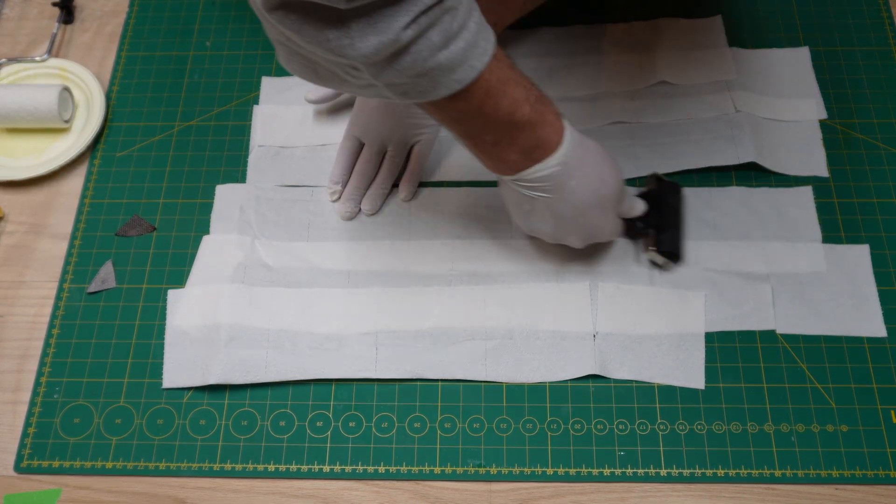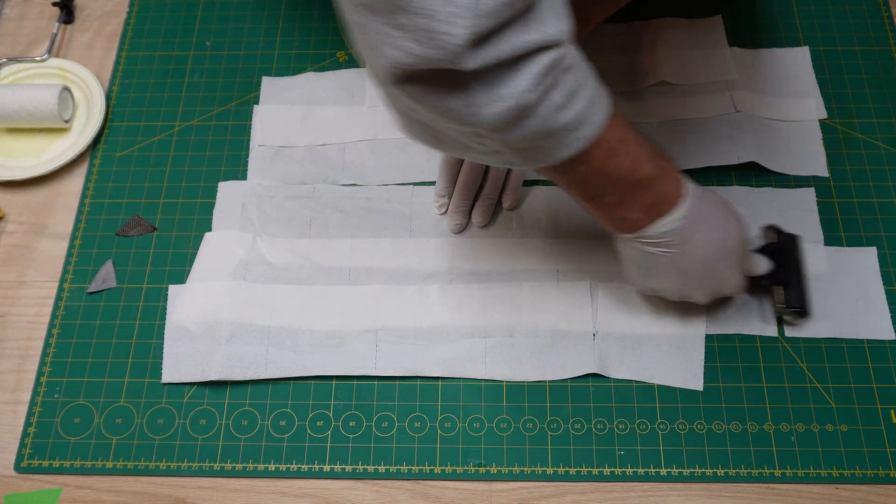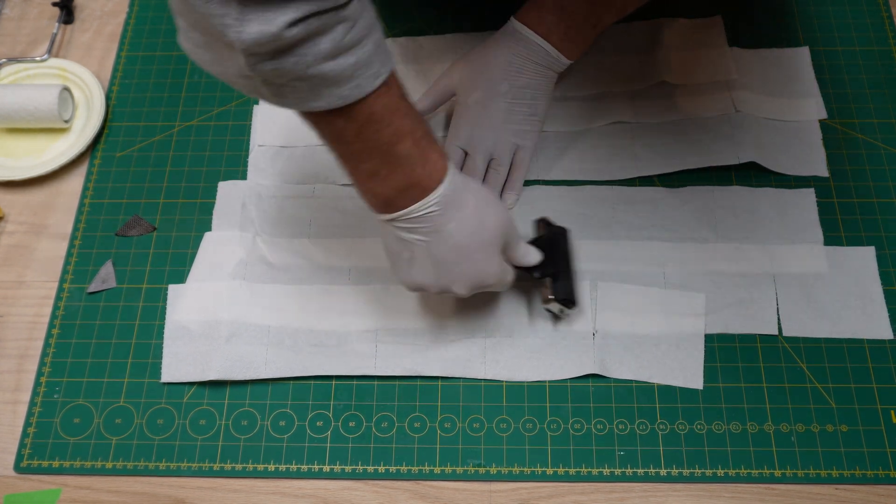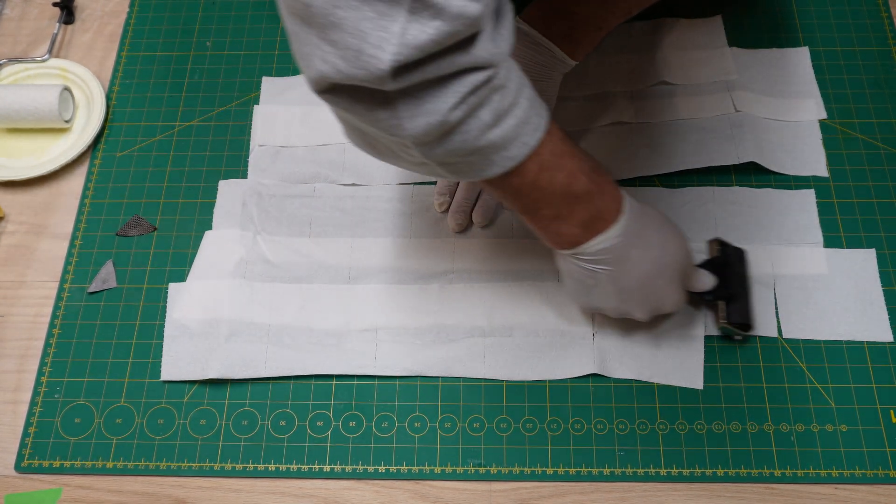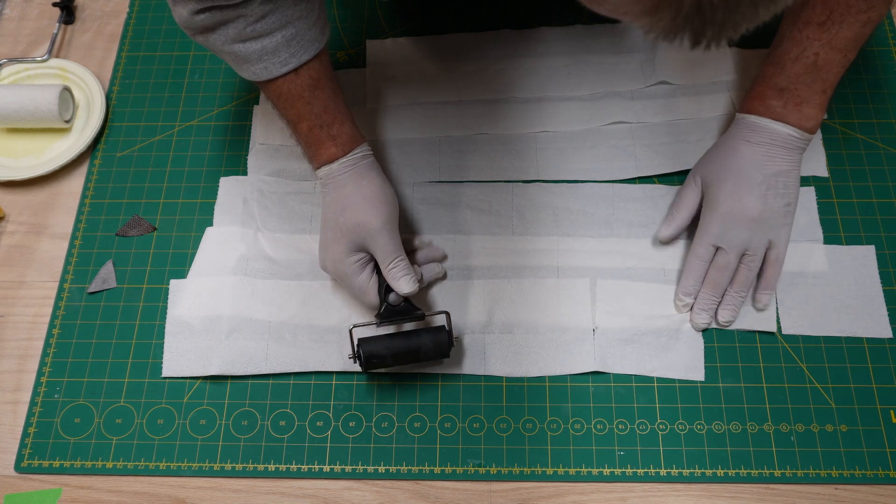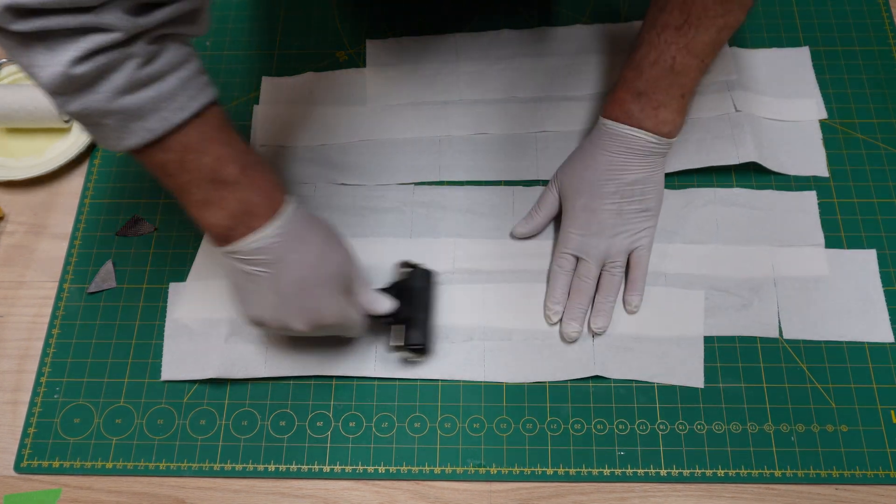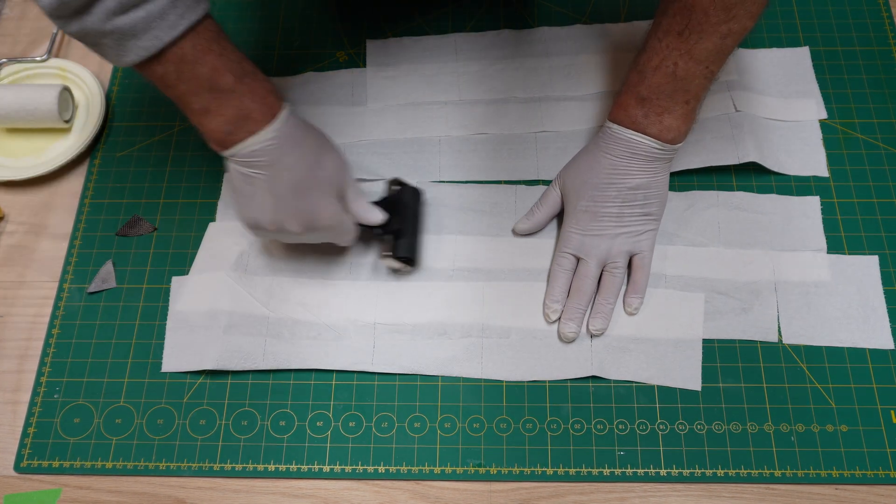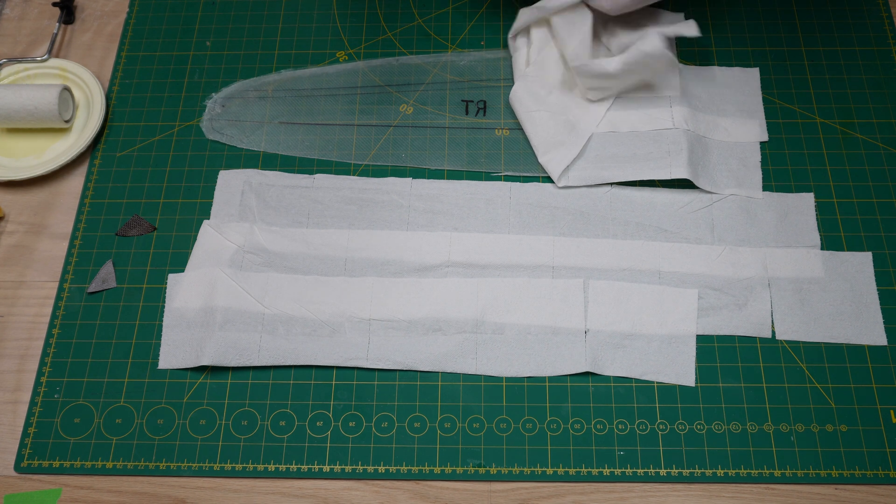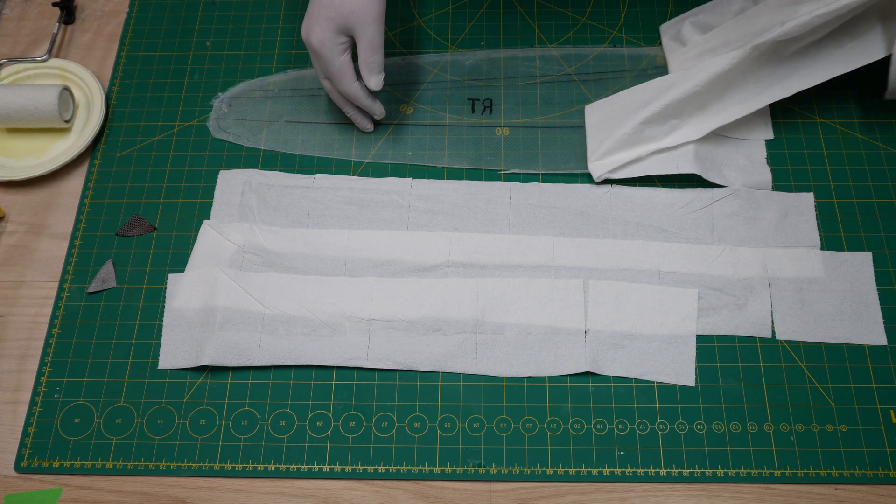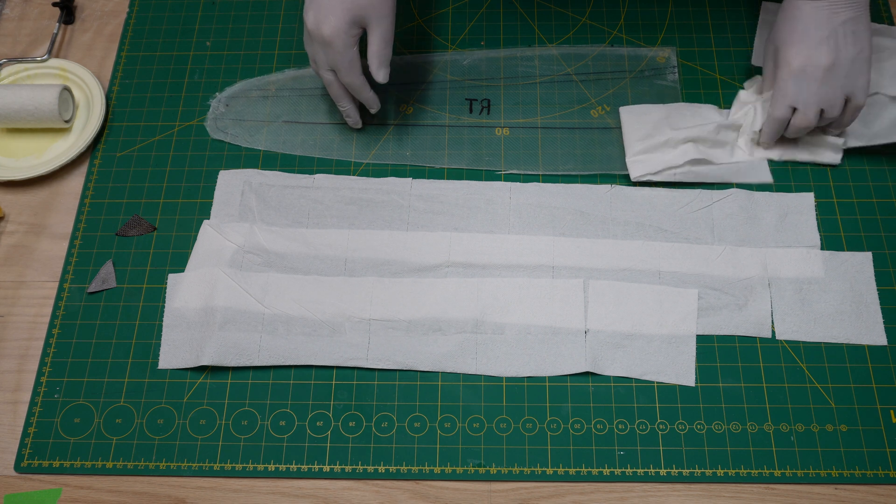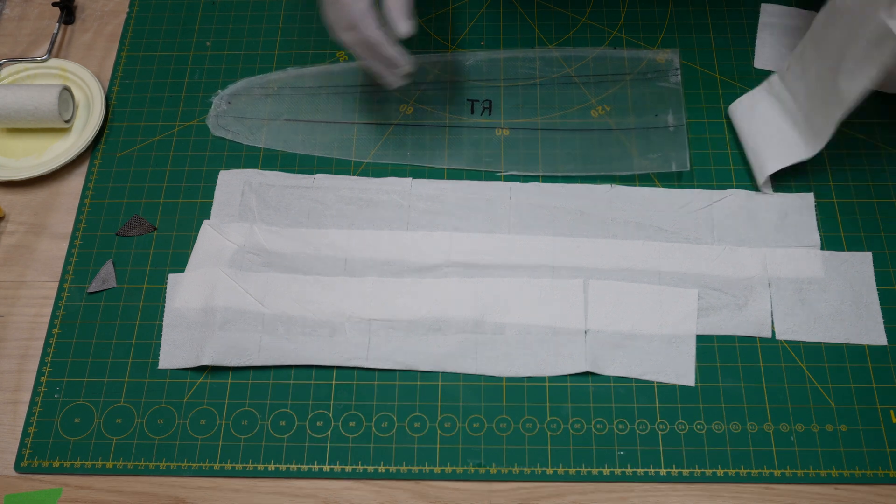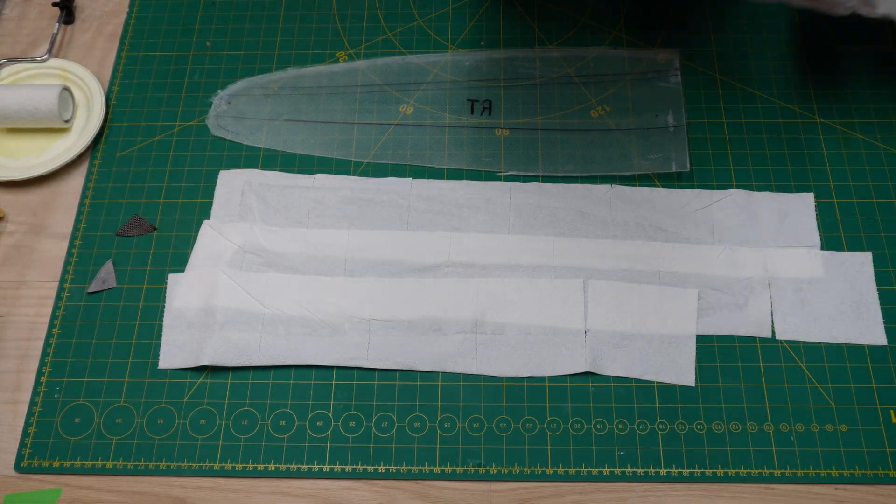I'm using a hard rubber roller, I think it's used in the printing industry, but I got it from Amazon. You want to roll out everything evenly and with the same pressure. This is gonna pick up quite a bit of resin, not all of it, but it will get quite a bit. It's gonna leave enough there to have the fiberglass saturated still.